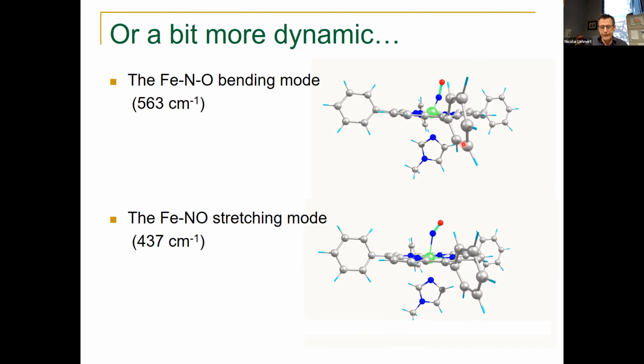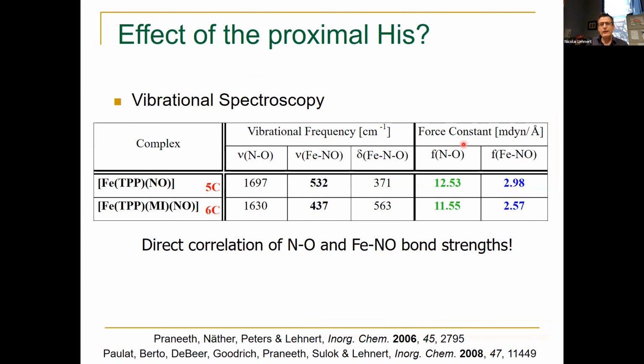So if we take all of this together, then we get to our table here, right? Where we can look now at the force constants of the NO bond and the iron NO bond. And this is the 6-coordinate complex. And then you can see when the imidazole falls off and you go to the 5-coordinate complex, both the NO bond and the iron NO bond become stronger at the same time, right? So we can also say there is a direct correlation of these bond strengths when we go from the 6 to the 5-coordinate complex. And what that immediately tells us is that this is an effect of the iron NO sigma bond. So going from 6 to 5 coordinate, the sigma bond becomes stronger, or going the other way around, it becomes weaker. So I guess I looked at it here the other way around, going 5 to 6 coordinate.